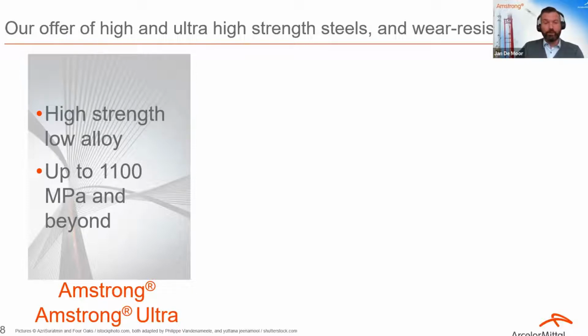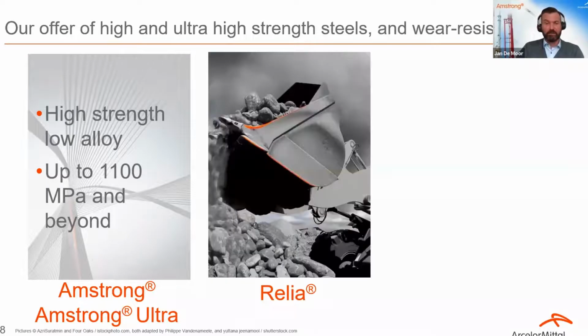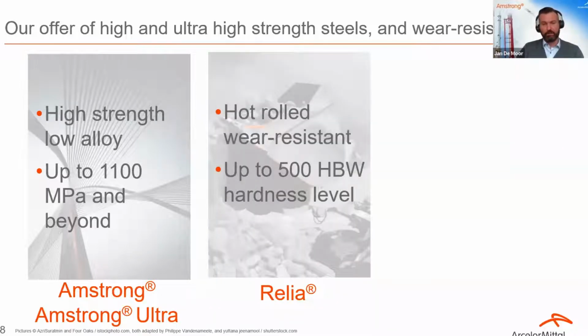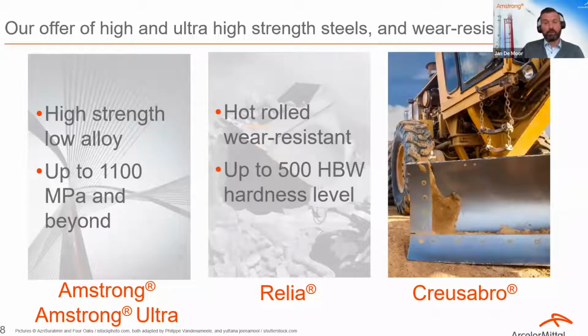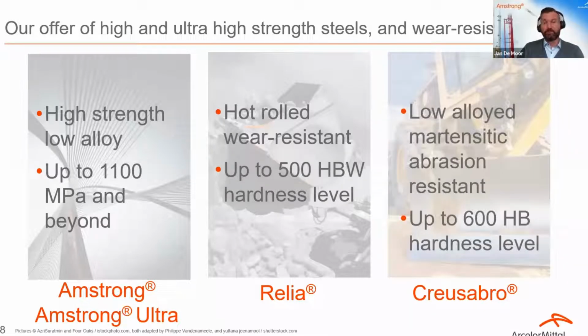Our offer of hot rolled wear-resistant steels, which we brand as Relia, in cut-to-length sheets and plates up to a hardness level of 500 Brinell, where the main use is equipment for excavation and bulk handling, crushing and screening, demolition, waste and recycling equipment, cement and other industrial applications. But we further expanded the range with our Creusabro discrete plate offer in low alloyed martensitic abrasion resistant plates up to even a hardness level of 600 Brinell for even the more critical wear parts.